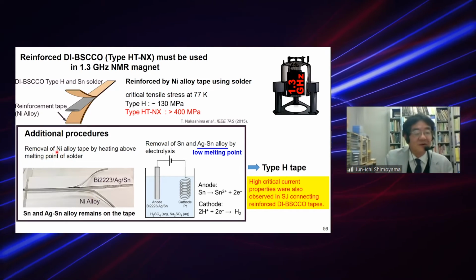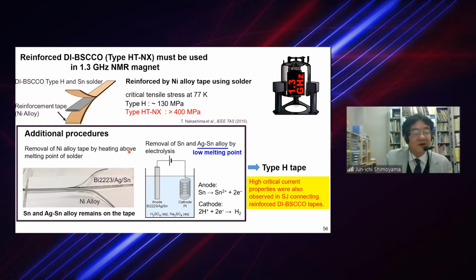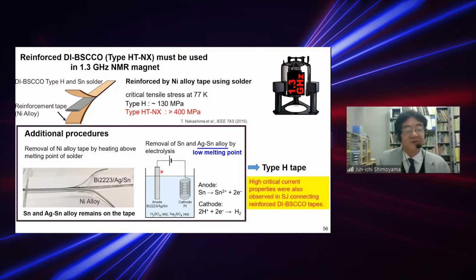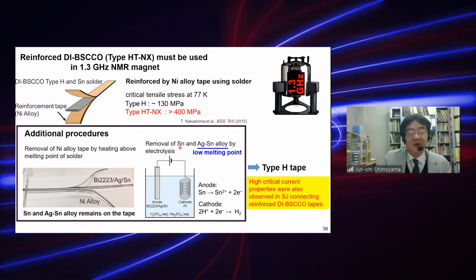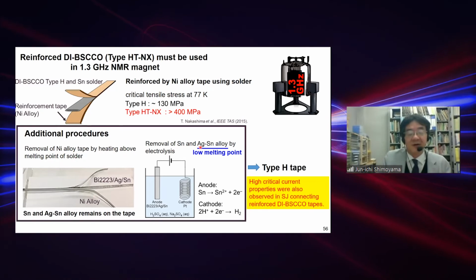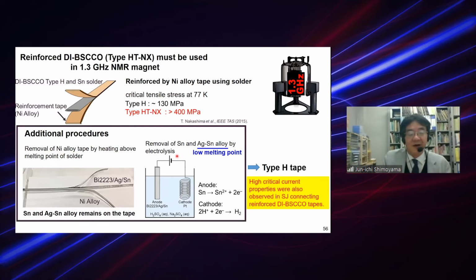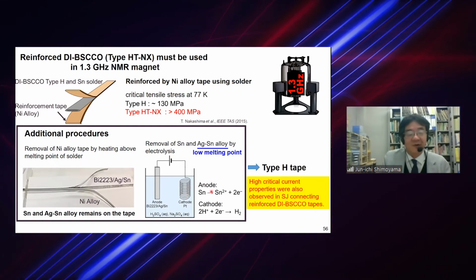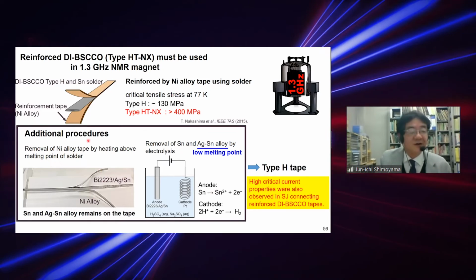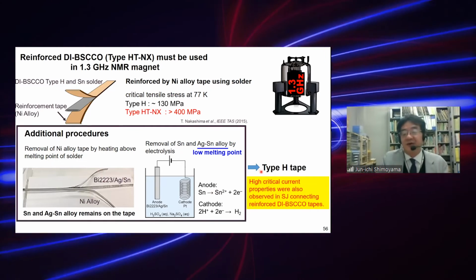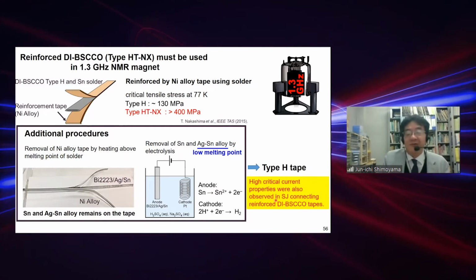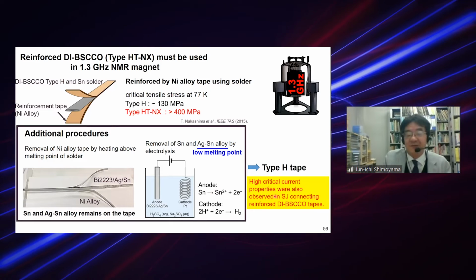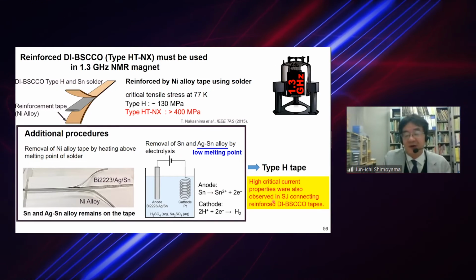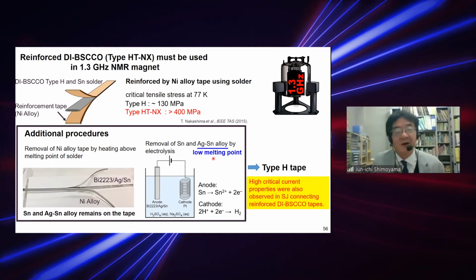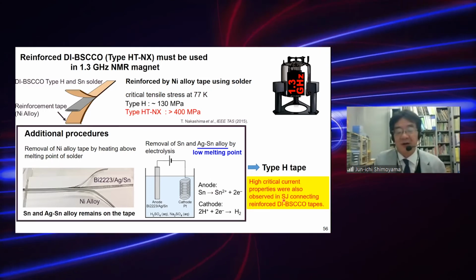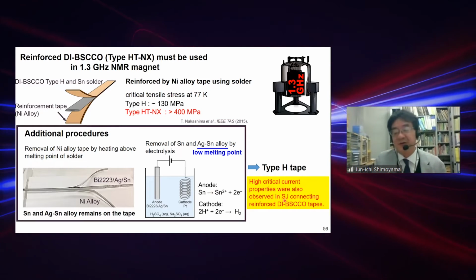To remove the nickel alloy tape, we heat above the melting point of the solder and remove the tin and silver-tin alloy by electrolysis, in this way. Through these additional procedures, we obtain Type H tapes. Therefore, high critical current properties were also observed in the reinforced tapes, even in the superconducting joint.